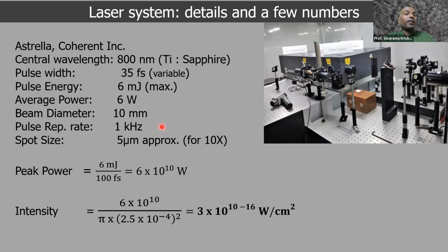These pulses are fired repetitively in a time series with a repetition rate of 1 kilohertz. This is fixed in the case of this laser, giving an average power of 6 watts, that is 6 joules per second. And we typically focus these down to best spot sizes of about 5 micrometers, which may be slightly on the lower side. Realistic could be like 10 micrometers, but that depends upon the focusing element or the microscope objective which we use.